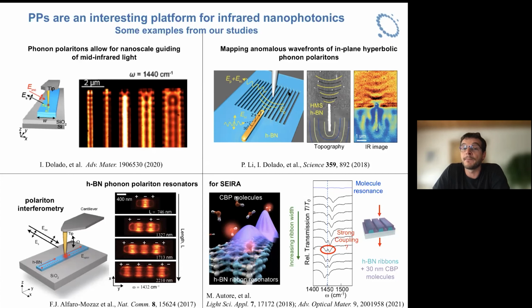And in this case, this surface acts as a metasurface, and exotic wave propagation occurs that we can see here to the right. I show a topography image where we see the pristine hBN, then the grating structure, and on top, we placed a metal antenna. This metal antenna acts as a light concentrating device, and it creates a bright near field at the edge, which launches polaritons that propagate along this grating. In this topography image, I indicated the wavefronts with which these polaritons propagate.